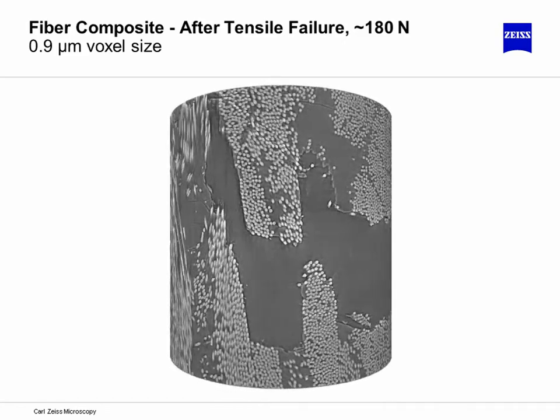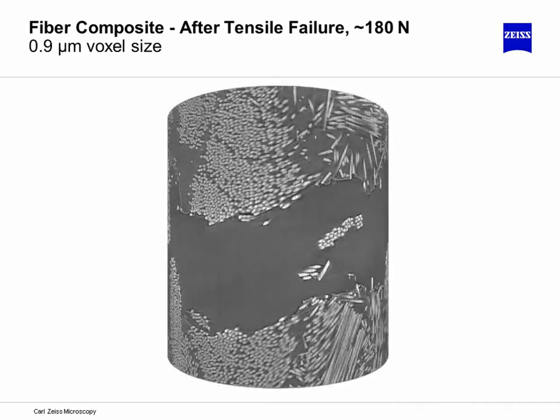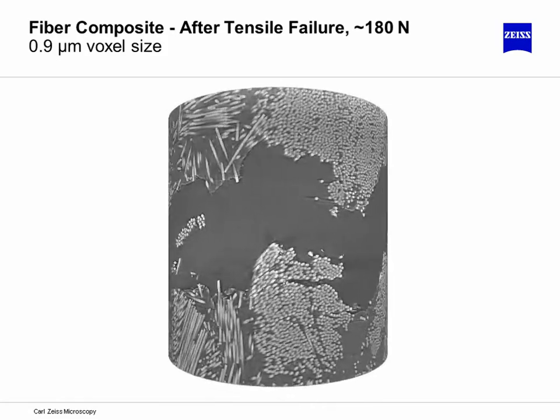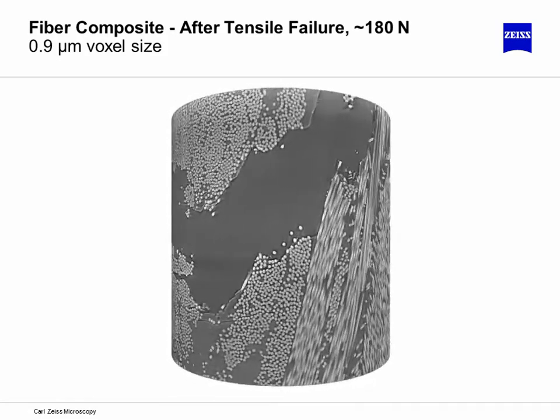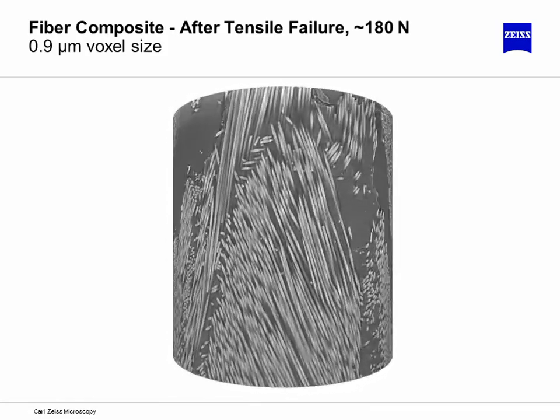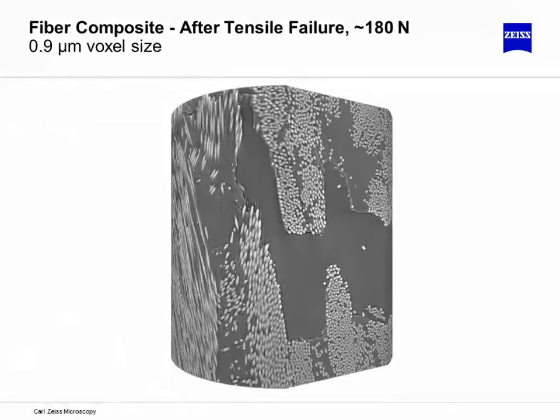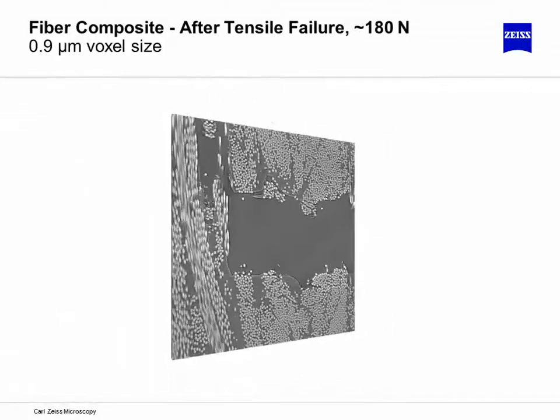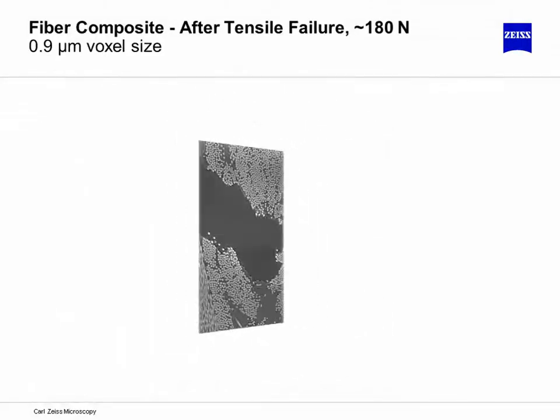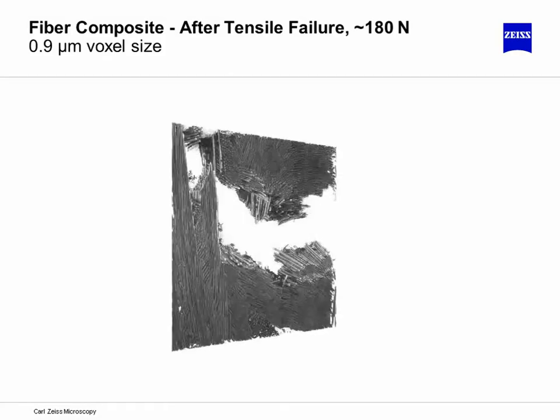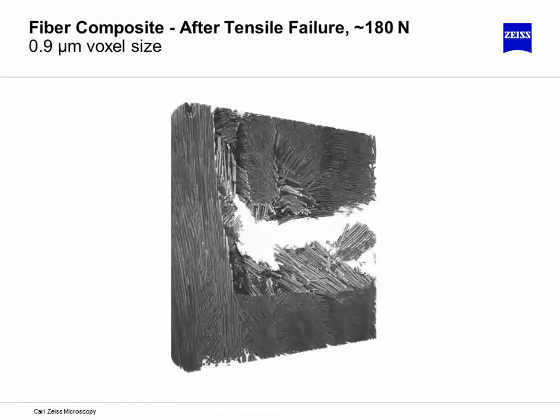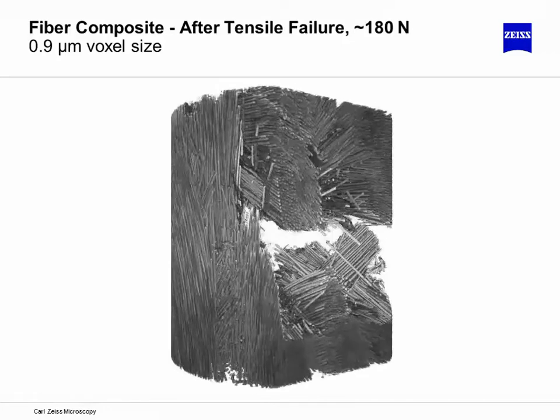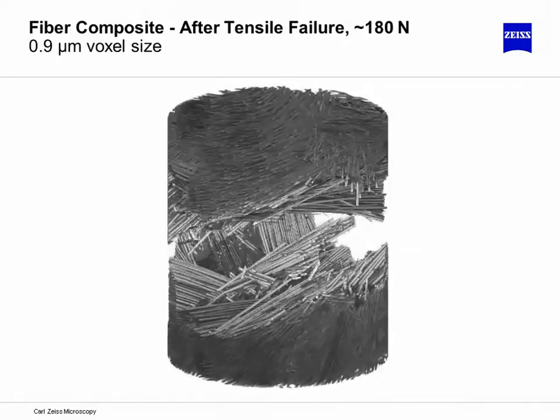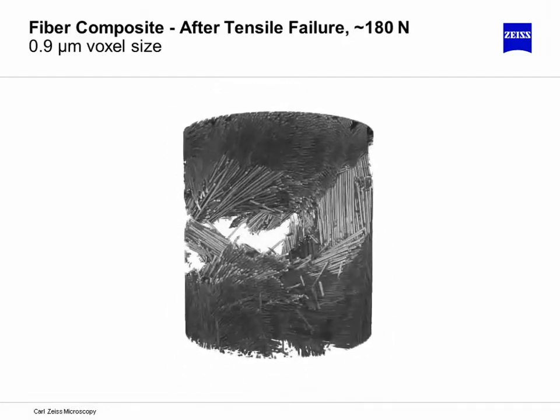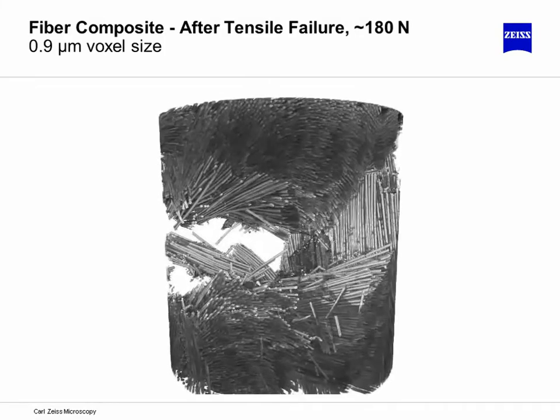Going into a little bit more detail on the Versa length scale, again, this is the submicron X-ray microscope. Looking at a movie here, which is playing of a fiber composite sample. This is almost a millimeter in diameter here with a 0.9 micron voxel dimension that was obtained. You can clearly see individual fibers. This is actually a fiber composite that underwent tensile load, which was then fractured.